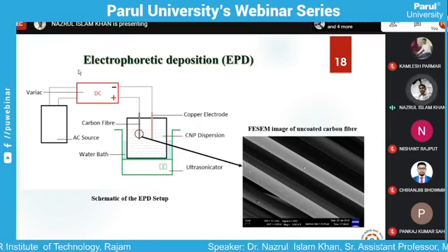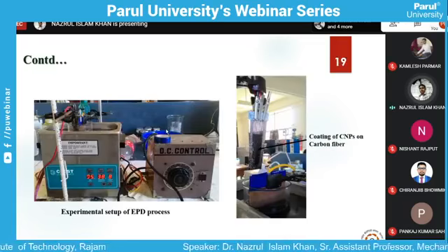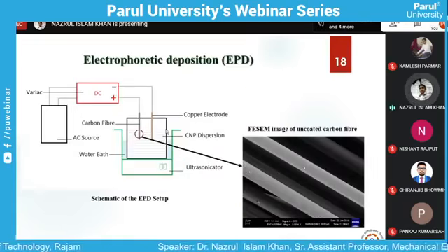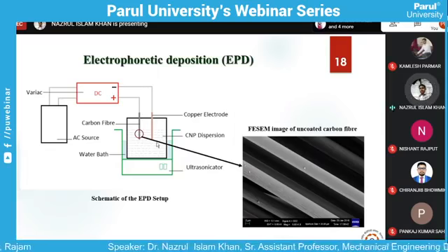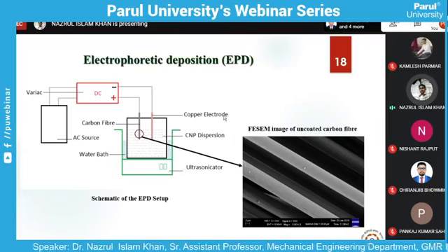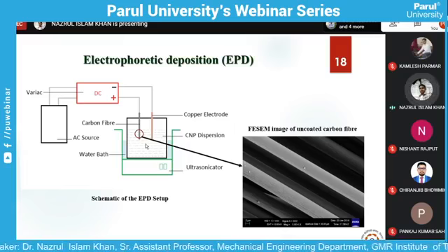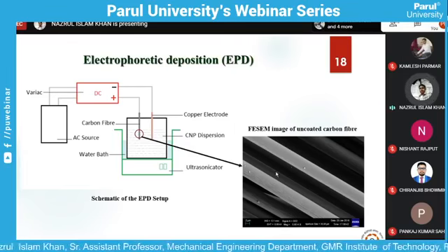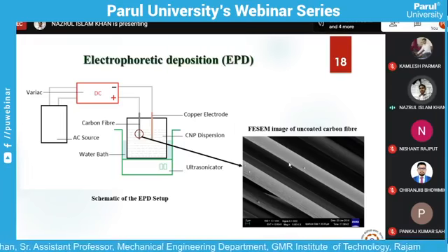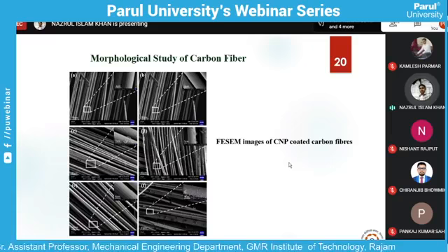So one of the techniques is electrophoretic deposition. What is electrophoretic deposition? If you disperse the charged filler in the matrix, and add the fiber, that is carbon fiber, in one electrode, and in another electrode you use some copper electrode or some other conductive electrode, what will happen is these charged ions of the nanofiller will be attracted towards the surface of the carbon fiber, and the surface of the carbon fiber will be functionalized using this kind of nanofiller.